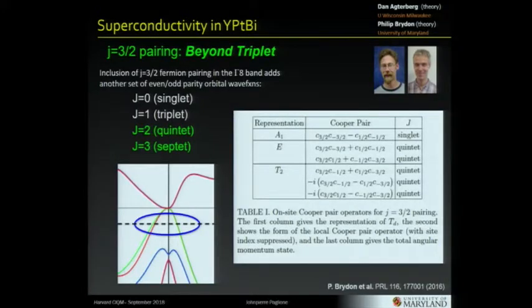This work that Daniel and Philip did was a whole calculation of all the possible pairing states given this band structure. And of course, as I alluded to, the interesting thing is that you go from the usual case where you have a singlet paired state of spin up and spin down 1/2, to the more rare spin triplet state where you have, let's say, spin 1/2 up and spin 1/2 up. But when you have higher spin species, you can go higher, of course. So you can go J equals 2 and J equals 3. Quintet and septet, I don't know what 7 is.